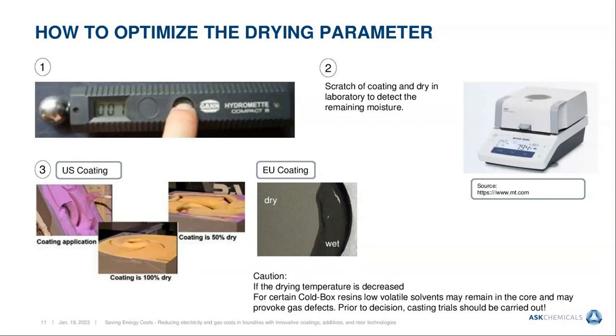However, you have to take caution. For instance, if you want to reduce your drying temperature to save energy, you must have in mind that cold box resins often contain low volatile solvents, which then remain more in the core and may provoke gas defects. So in any case, prior to a decision, you have to do casting trials to avoid any trouble.